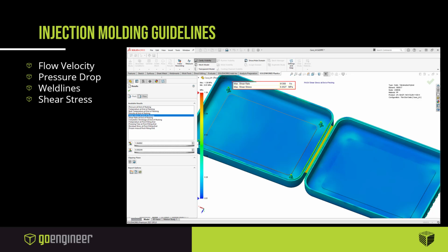Our restricted area also will cause shear stress in the material. So your material's flowing through there and you have shear stress on the plastic material. That could cause degradation in the material if your shear stress is over the maximum recommended shear rate and shear stress for that material. One thing that shear helps with in a molded hinge is shear heating in the plastic. So you have the plastic flowing through the part, it hits this restriction, and it starts heating up. It heats up and flows more smoothly through the hinge, and then it'll start cooling down again. But you just want to make sure that your shear stress and shear rate don't go over the maximum, or you're actually going to overheat the material and then it'll start degrading, and then you're going to have a weak hinge. So there's a balancing point in there. We have to look at all of those things with our thicknesses and everything.